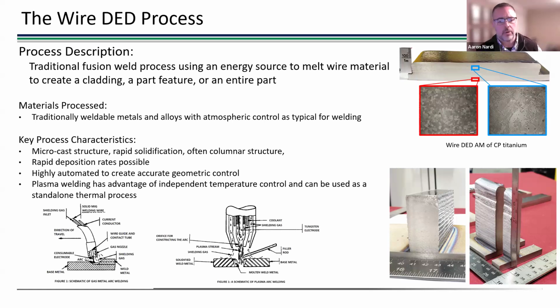There are certain characteristics of that process, but also certain limitations with what you can do with it. For instance, you always have to have filler metal. You can't weld a material without filler metal, just melting the two materials together. Now, the plasma arc process is a little bit more like a TIG process, but instead of having the arc between your electrode and your substrate, you're creating a plasma jet with the arc, and that plasma jet, kind of like a laser, hits the substrate and heats it up, and then you feed a wire, a filler metal, into that arc. So we use both processes. We use the plasma arc a little bit more often because you have a lot more control over that process than you do with the more MIG-based process.